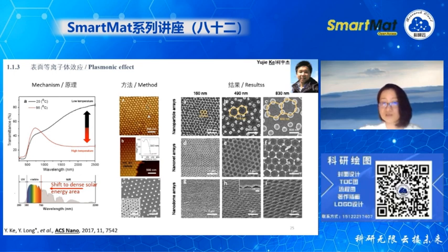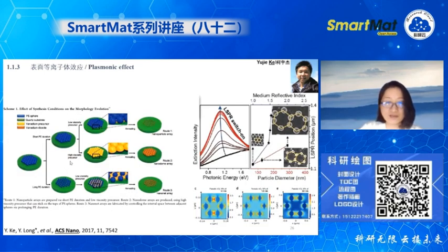So we also came up with a method using PS spheres. We simply control the PS sphere diameters and the etching time. Again, some very simple ways. So we can get nanoparticles with different periodicity, nano nets, and nano dome structures. So structures with different periodicities can be fabricated. This is a process. This is a PS sphere we just assembled. Then we put vanadium dioxide on top of it. Then we just get rid of these PS spheres. So we can get all sorts of different structures. Okay, as you have already seen by SEM, we can really do it.